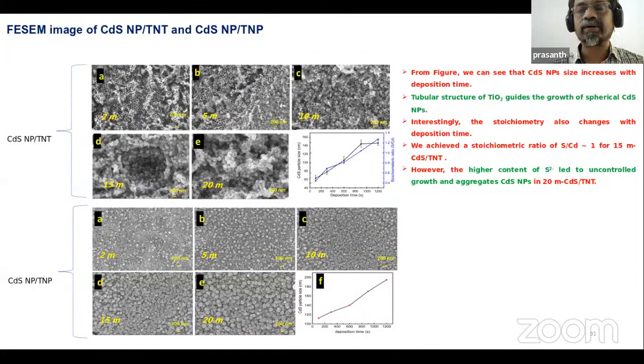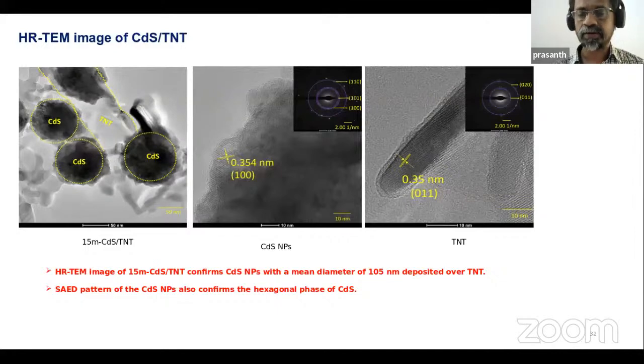So when we are working with this TiO2 CdS structure, the main problem is its instability. CdS is not very stable with the heterostructure formation. So you have to make a proper stoichiometry by adjusting the deposition of CdS. That means you have to make a correct stoichiometry of CdS, 1:1 proportion. So we played with the time of deposition, and at what time you are getting the right stoichiometry of the CdS. That shows a better performance of the device for hydrogen production in the electrochemical cell.